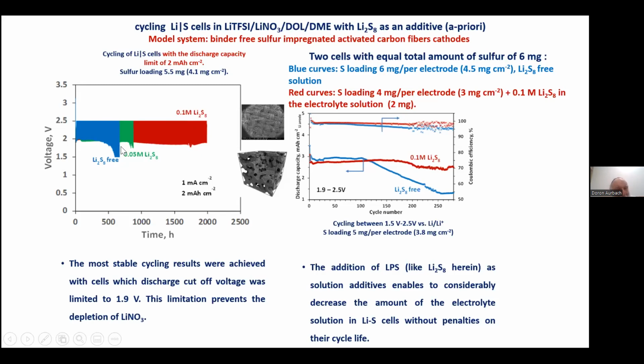So without our additive, the passivation of lithium is not strong enough, so we have failure after a few hundred hours of cycling. But with our additive, when we have a priori the sulfide and now the nitrate in the electrolyte solution, it immediately oxidizes the lithium sulfide to a lithium-sulfur-oxygen compound, and from the very beginning the lithium is well protected. Now we can come up with continuous cycling. These are simply continuous voltage profiles during the galvanostatic cycling of lithium-sulfur cells, and we demonstrate that here also we can reach a reasonable stability.